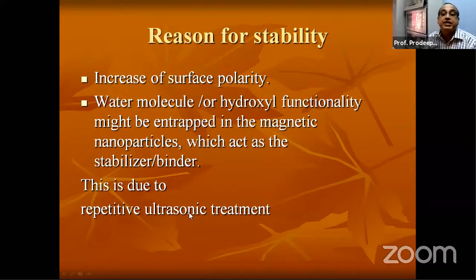It is due to repetitive ultrasonic treatment. Actually, according to our theory of ultrasound, if you keep irradiating any kind of solution under ultrasound, then inside the solution there are certain hotspots where the temperature goes very high. Although the overall temperature of the solution is not very high, they create some hotspots inside the solution. So the hotspot temperature goes very high, even more than 500. So it causes disintegration of the water molecules, and that gets absorbed onto the surface of the cobalt ferrite nanoparticle. And since that kind of aggregation takes place on the surface or inside the cobalt ferrite, there may be some cracks. So this acts as a stabilizer, and since it increases the surface polarity, it becomes stable.